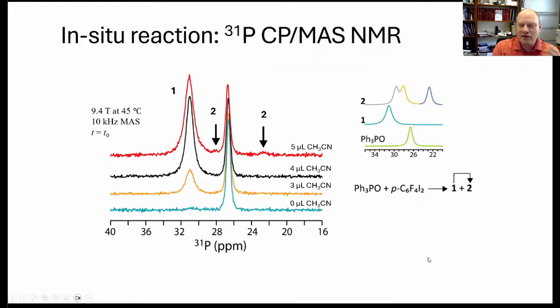So here's an example of this phosphorus 31 NMR spectrum that we get. So at time 0 is the blue or cyan trace at the bottom. We just get a peak for our triphenylphosphine oxide. If we do what we're calling time 0 with 3, 4, or 5 microliters of acetonitrile added, we can see already right away formation of product 1. And with 5 microliters, already a little hint of formation of product 2.